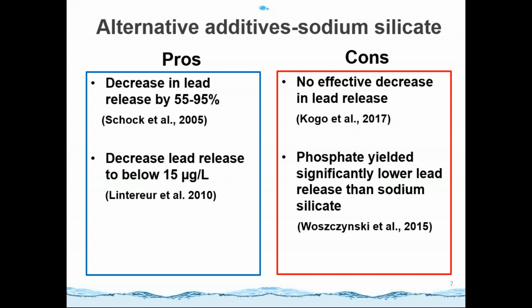In 2017, a study indicated no effective decrease in lead release when they investigated the lead concentration in a galvanic lead pipe. And in Halifax, a researcher compared the lead concentration in the sodium silicate treated system and found the lead concentration was relatively high compared with the orthophosphate treated system. So in general, I think the application of sodium silicate is controversial in the literature.